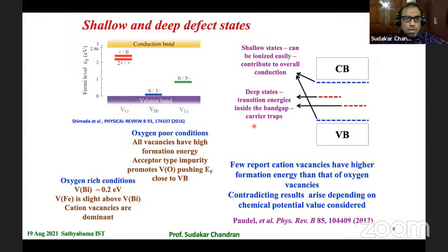It's important to understand the defects that would exist in this material. For example, you have a valence band and conduction band. It's an insulator, roughly about 2.8 electron volt band gap. Oxygen vacancies are pretty common in this structure. Specifically, when you prepare the materials in oxygen poor conditions, you would end up with oxygen vacancies that lie pretty close to the conduction band. It could be neutral or charged state, but mostly in our studies we found it's a neutral state.